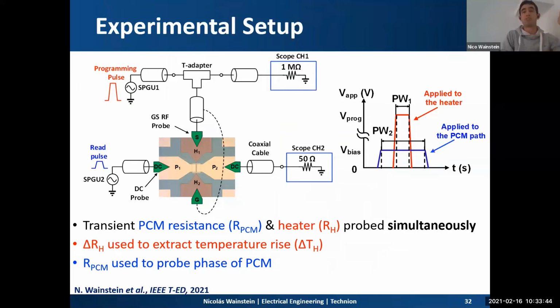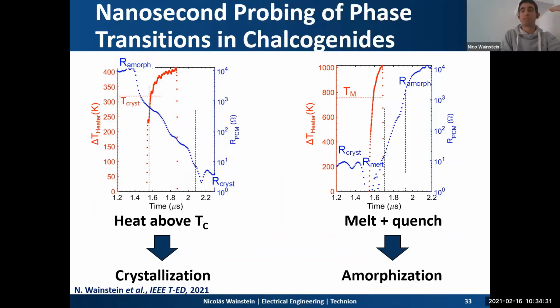Our setup allows for the first time to probe simultaneously the phase transition while the actuation pulse is applied. In our setup, we connect the heater in parallel with the scope in high impedance, and the PCM path is in series with the scope to probe simultaneously both paths. By applying two pulses, as we've shown here, we can probe simultaneously the resistance of the PCM and the heater. The resistance variation of the heater, as I mentioned before, allows us to calculate the temperature variation on the device, while the resistance of the PCM allows us to probe the phase transition properties, such as the crystallization and quenching time, resistivities, etc.